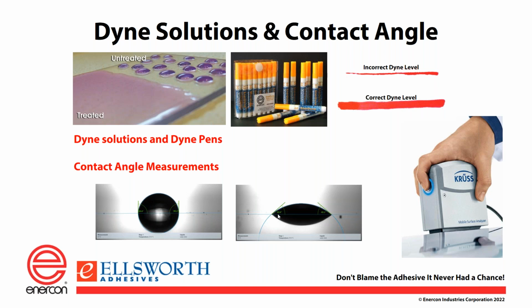They're not perfect measurements. They are not absolute measurements. And by that, I mean, if I measure my phone, it's 5 or 6 inches across, and I mail it to you wherever you're at, it's still going to be 5 or 6 inches across. Contact angle and dyne solutions are not that way. There's a lot of atmospheric things that are going to affect that and the way the treatment method is going. So you can get slightly different numbers, but what we're really looking for is a delta, a large change in either the dyne or the contact angle that shows that we're increasing the surface energy.